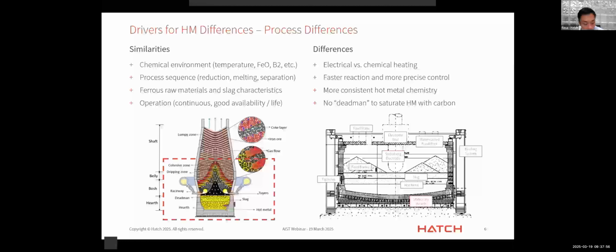Of course, there are a lot of differences as well. The big fundamental driver is the difference in the source of energy. Whereas the blast furnace is predominantly chemically driven, with coke and hot blast and PCI or whatever energy source you inject into the furnace, the ESF is predominantly electrically powered. Whether it's arc heating or resistance heating through the slag, the majority of the power comes from electricity. Therefore, there is an advantage in the electric smelting furnace that allows much faster reaction and more precise control of the process, whereas the blast furnace burden descends and completes the reaction in the order of multiple hours, 6 to 8 hours, if not more.